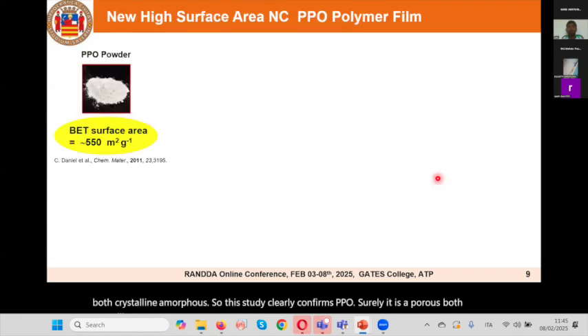Coming to the PPO powder, Professor Daniel characterized this semi-crystalline PPO powder with a very high surface area, 550. This surface area is very huge. It is mainly contributed by the nanoporous crystalline phase. The nanoporous crystalline phase is mainly contributing to this.